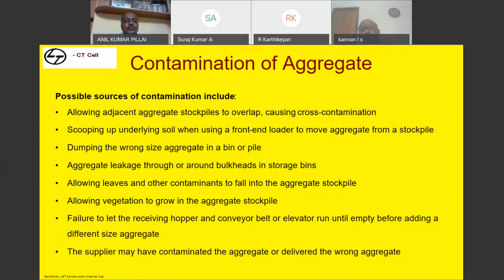Leaves or other contaminants falling on the aggregate stockpile. Especially sand, the tendency is people stack it near a tree, and the leaves will fall. What happens is the organic impurities start making vegetation grow. You can find a lot of grass growing. That is a clear indication of organic impurity, plus silt and clay is also more, because otherwise, if silt and clay are not there, nothing can grow in sand, since sand is a cohesionless material. Some cohesive media is needed for the vegetation to grow. That is a clear indication.